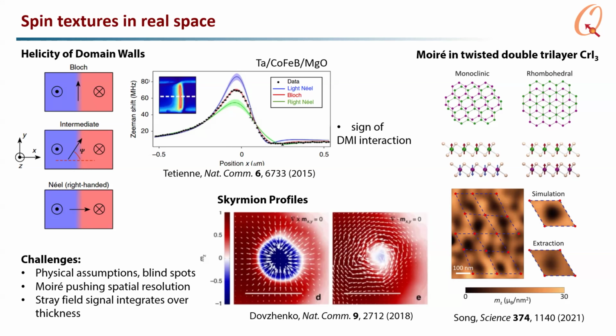But there are some challenges towards this magnetization reconstruction. In particular, you can't tell the difference between left Bloch and right Bloch. The component of the spin that's parallel to the domain wall, we're not sensitive to that. And for the skyrmion reconstructions, they had to make some extra physical assumptions. Also, we integrate over the thickness of the sample, so it's not really layer resolved. And for Moiré physics, the spatial resolution is pushing what we can do. At the smallest twist angles, people can get maybe 100 nanometers, but for larger twist angles, the Moiré period is too small.